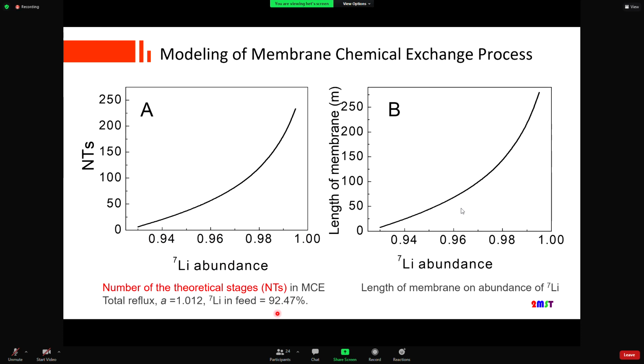This graph shows that we can design the system based on our previous results. You see here, when you want to reach 99.9%, you need more than 200 modules, 200 theoretical stages, which is slightly larger because our module is less than 1 theoretical stage. So we need about 280 meters of length in the system to reach 99% lithium-7 abundance.